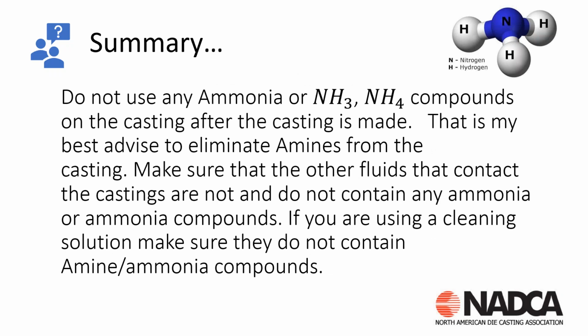So in summary, I'm going to say, don't use ammonia, don't use ammonium on any post-treatment of the die castings. Have the die castings made, you trim it, you're prepping that casting, make sure that any cleaning solutions don't have ammonia or any type of ammonia compounds in them, and then that's going to eliminate any amines from actually just laying on the surface, or any potential ionic bonds that could form if we had the correct positive and negative charges between those different items.